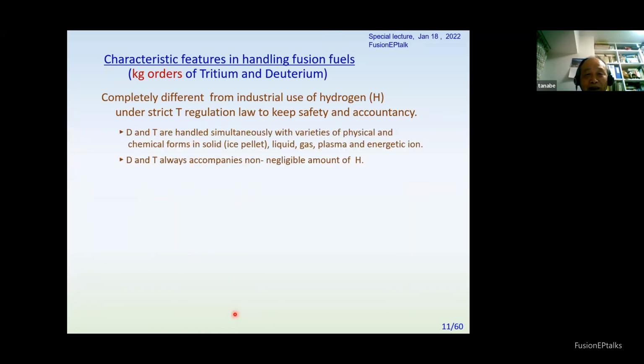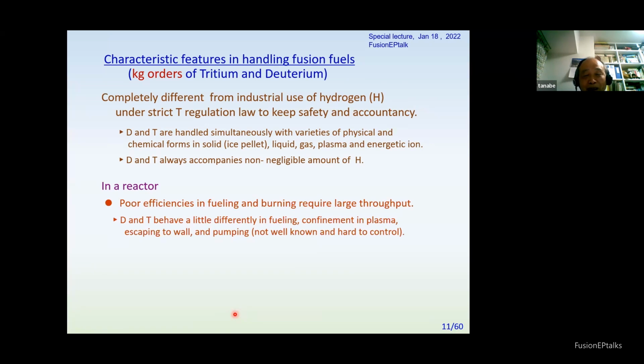So D and T are handled simultaneously in a variety of physical and chemical forms: solid, liquid, gas, plasma, and energy. So a variety of energy forms. And D and T always accompany a non-negligible amount of hydrogen. Please remember, this is a very important point. In a reactor, there is poor efficiency in fueling and burning, I will show detail later. Fueling in plasma and burning in plasma require large throughput. D and T behave a little differently in fueling, confinement, escaping from the wall, and pumping because of the large mass differences. H, D, T mass differences are 1, 2, 3.